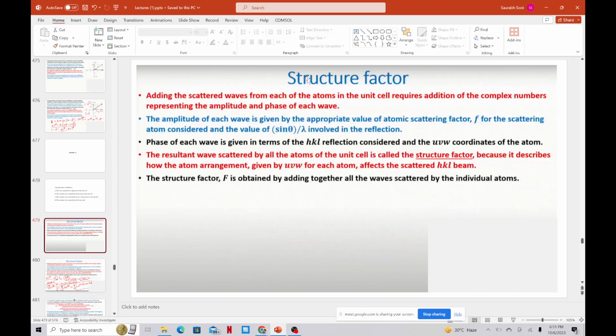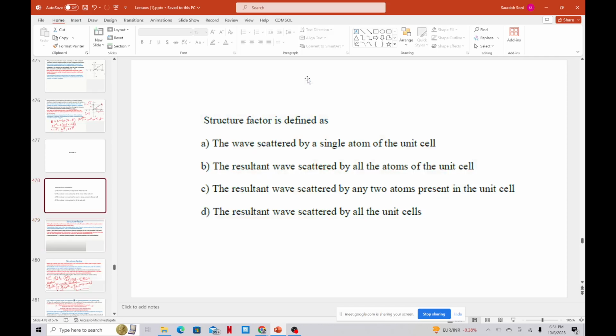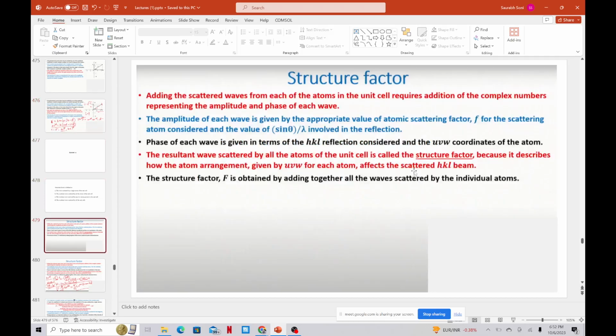Structure factor. So this is the resultant wave scattered. It's not individual. The resultant wave is scattered by all the atoms of the unit cell, not one particular atom or two atoms, but by all the atoms, and it is a resultant wave. That is your structure factor. So the resultant wave is scattered by all the atoms of the unit cell. Not a single atom? No. Any two atoms? No. By all the atoms of the unit cell. The structure factor is obtained by adding together all the waves scattered by the individual atoms. How is it obtained? You have to add together all the waves scattered by the individual atoms.